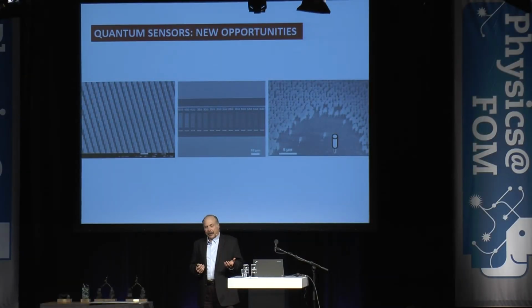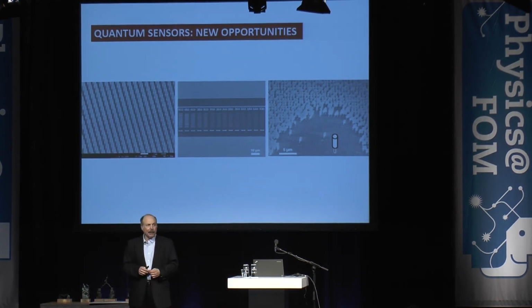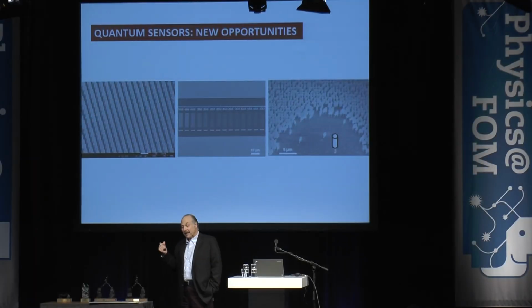All of this work was done by looking at quantum states built inside a material. Now, what happens if you can take them off the material and be able to move them around? And so a lot of people in the world have been thinking about building quantum sensors. So on the left is an image of taking some films of diamond that were grown synthetically by chemical vapor deposition in our own laboratories, etched into small pillars over a wide range of sizes and shapes. And if you look at the drawing on the right, sorry, the SEM image on the right, it's definitely not a drawing, a little jet-lagged. You can see that these small diamond pillars are weakly attached to the surface with small polymer threads.